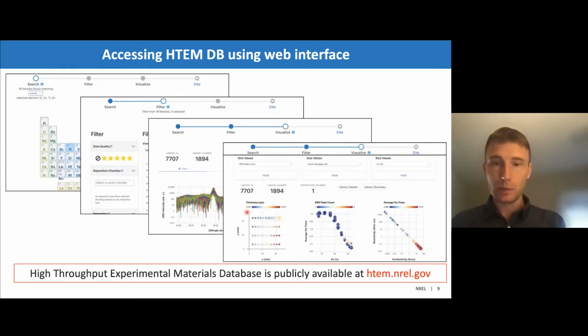For example, here we plot the thickness of the sample across the sample library. You could see a little bit of thickness gradient going across the X and Y dimensions of that sample library. Or you could do cross-correlative plots, for example, choose to plot the average visible transmission as a function of tin content of that sample, and color the plots by, for example, the number of peaks that exist in X-ray diffraction, or do the same type of plots with resistivity or conductivity or bandgap of the material that have been extracted from these data. This is a more simple way of visualizing the data, and the one that works well for people that are just interested in finding out what kind of materials we've been working on, what synthesis conditions we use to grow these materials, and what properties they might have.